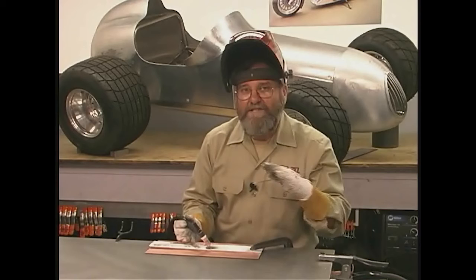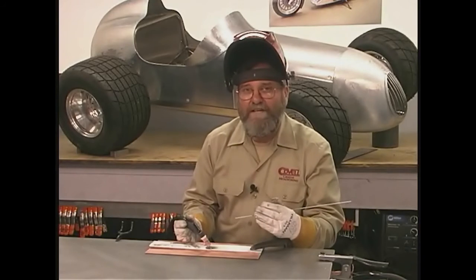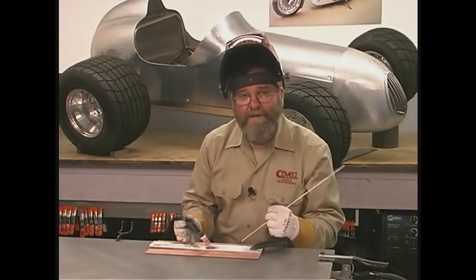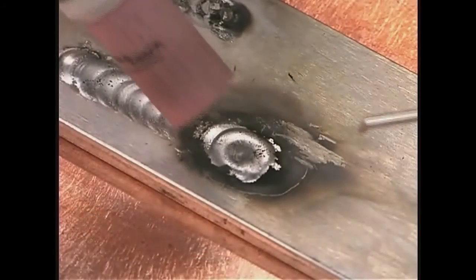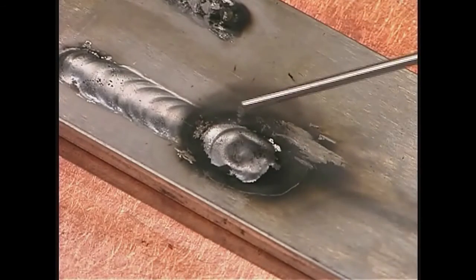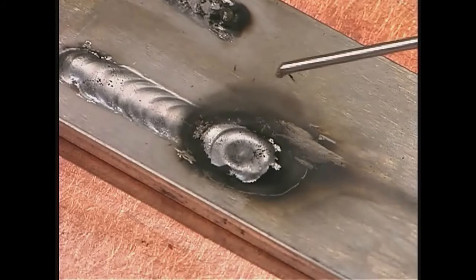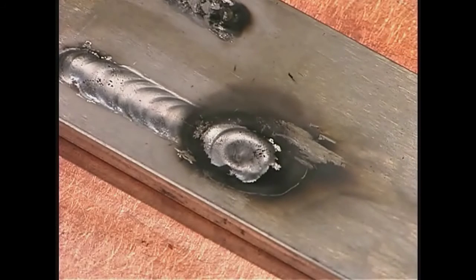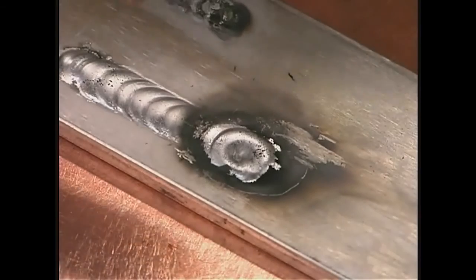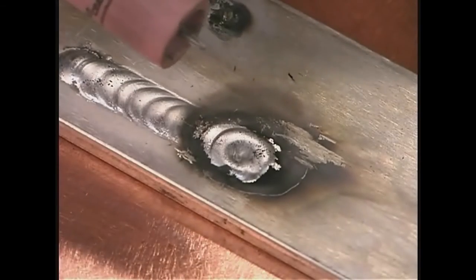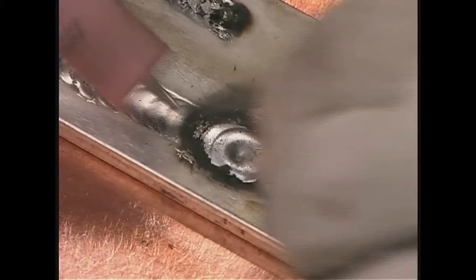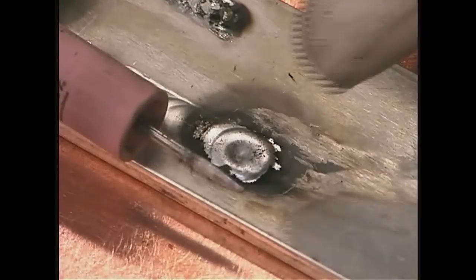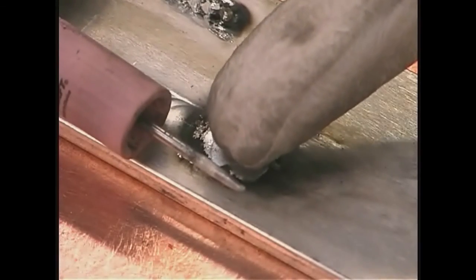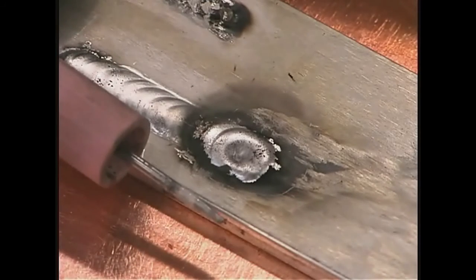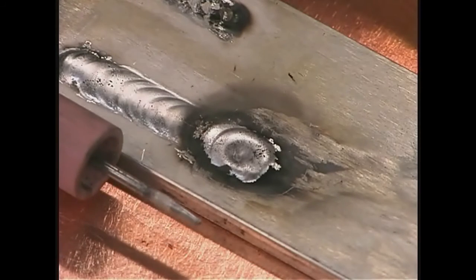And believe me, this is going to happen to you again and again as you start refining your technique of TIG welding. Let's take a close-up look at what the problem is. So you can see what a mess it makes of the weld area once that electrode gets contaminated. You can see the big black smudge around the weld. The problem is that when I touched the filler rod to the electrode, the filler rod actually melted and parts of it adhered to the tungsten electrode. And until I clean that off by sanding, I'm just not going to be able to make a nice weld.